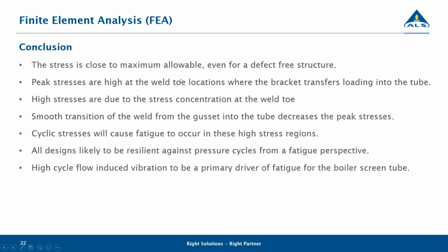Then when we put the bracket geometry in, the peak stresses at the toe, where the bracket transferred the load into the tube, was very high and concentrates at the weld toe. And then obviously the smooth transition there in that area would help. And the cyclic stresses in that area will cause fatigue to occur at that location, which we've seen on site as well. Most of the designs would be resilient against pressure cycles from a fatigue perspective, but when you look at high cycle fatigue, that's probably where the issue lies.